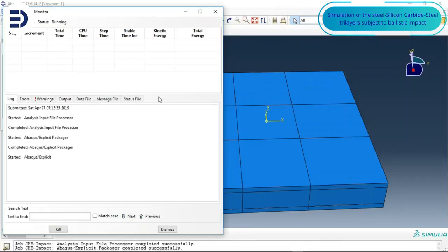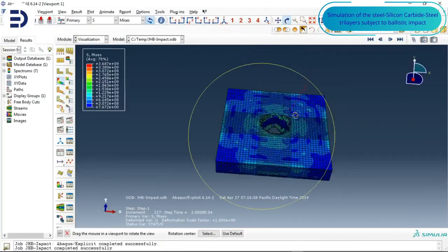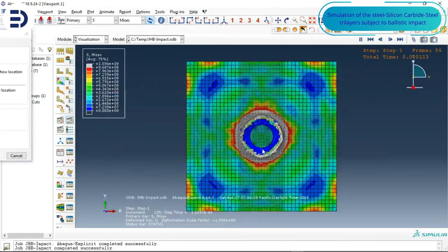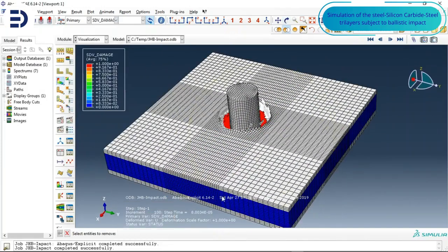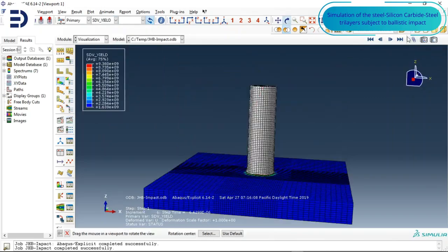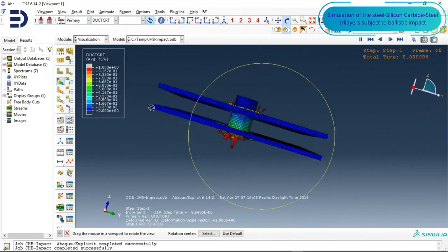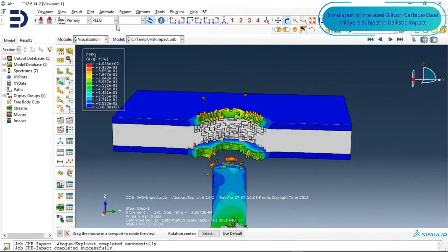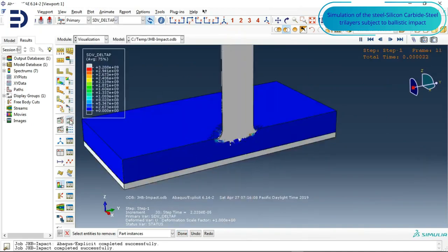In addition, the JH2 model incorporates a more detailed damage evolution law and provides a better representation of high strain rate effects. It explicitly accounts for hydrostatic pressure-dependent strength and failure, and supports both tensile and compressive failure modes. These enhancements enable the model to capture complex failure mechanisms such as progressive fracture, crushing, compaction, and fragmentation with higher fidelity. Due to these capabilities, JH2 is widely used in advanced simulations involving armor ceramics, hypervelocity impacts, and penetration mechanics. The model has been extensively validated against ballistic experiments and is commonly employed in high-fidelity military and aerospace applications.